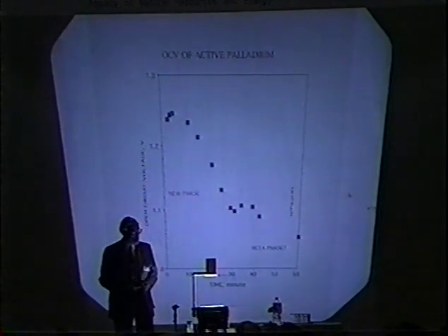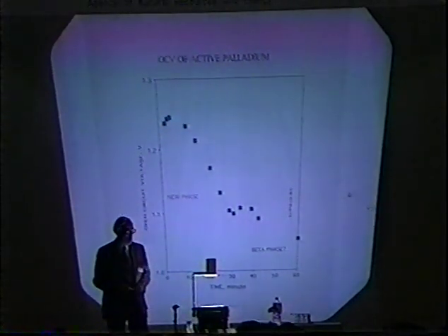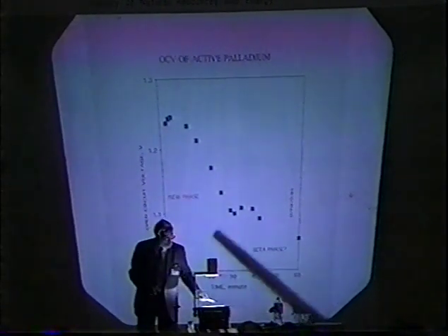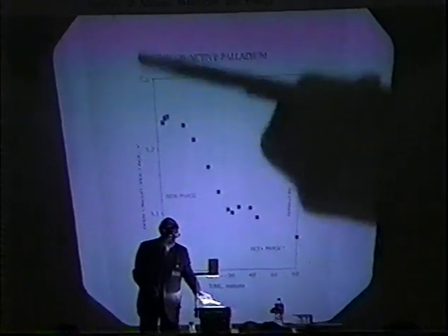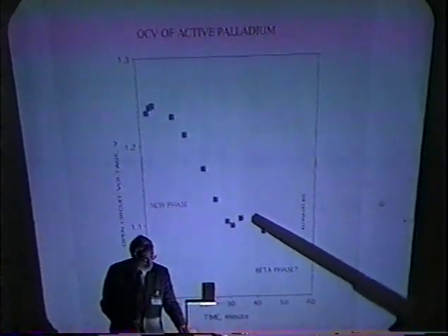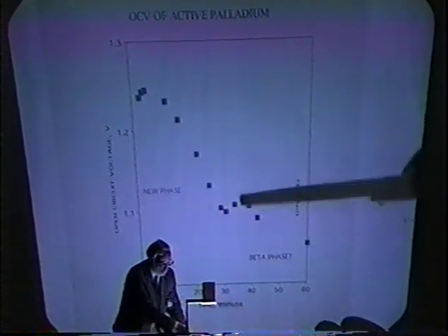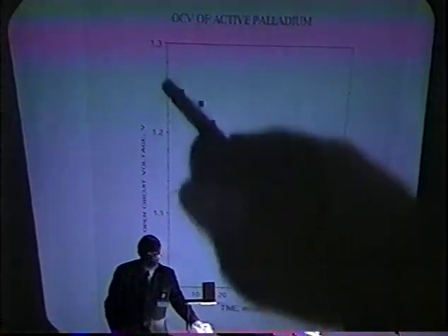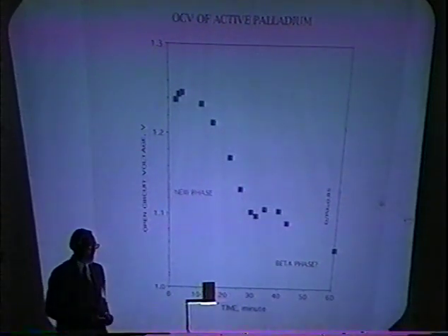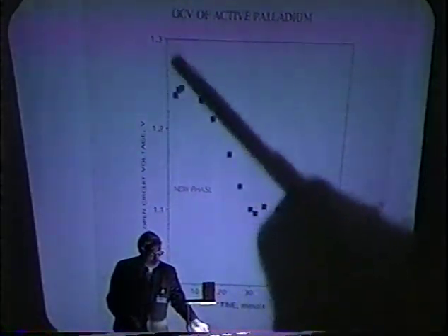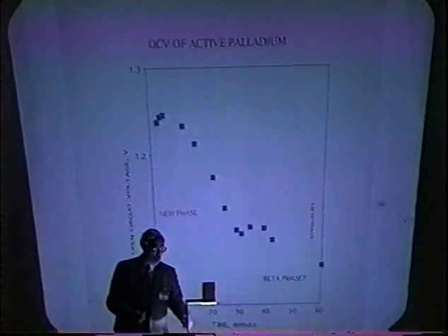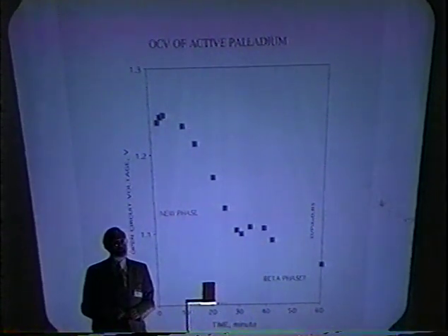A material that has made excess energy, or was in fact making excess energy when the sample was turned off, 4.5 watts, shows a different effect. Here we have an open circuit voltage which is very large, 1.25 volts. I've seen values somewhat higher than that, but that's up in the high range. If that loading is turned off, so it's allowed to deload, you see it come down, but then there's a little rest here and it goes down again. If this curve is followed on down, it behaves the same manner as the one I showed previously. That is, it follows on down and then drops down to zero. In other words, this is characteristic of the beta phase, but then there's something else on the surface which was not present in samples that did not make excess energy. And I believe this is the nuclear active phase that is required to be made, and it has a much higher composition, or at least a higher chemical activity than does beta palladium.